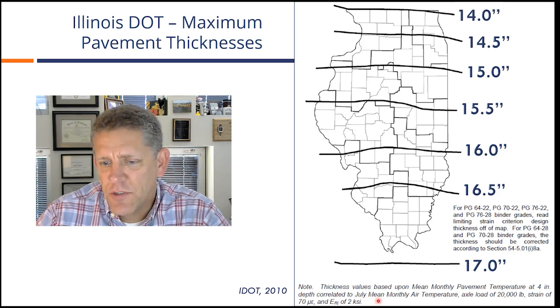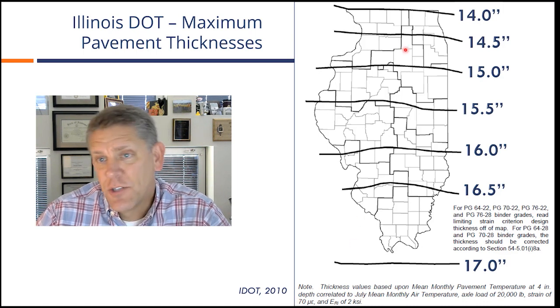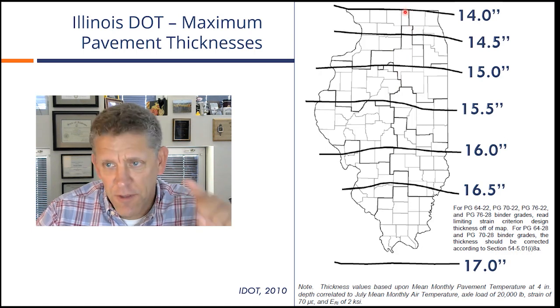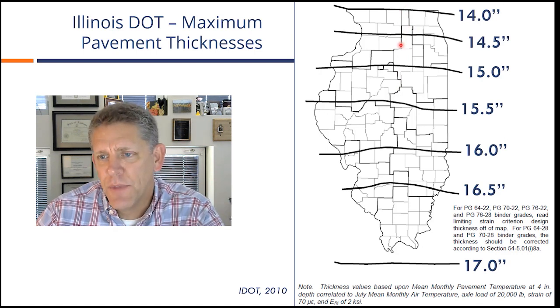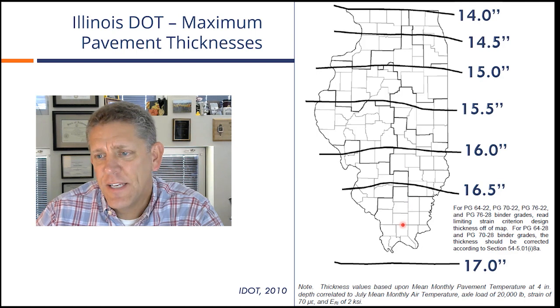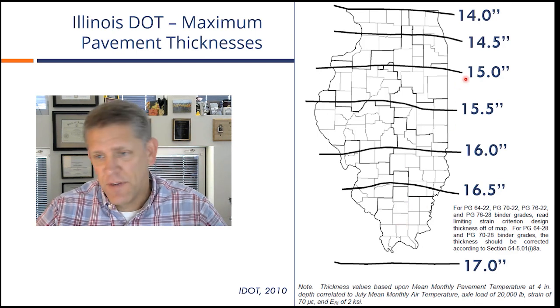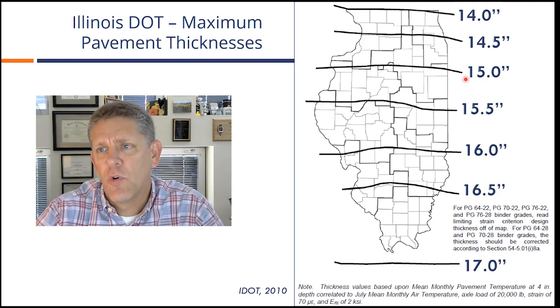The hottest month they use is July. They have some other assumptions in there. They use a pretty conservative strain level. And essentially they've gone through and done the computations, and the further north you are, the relatively thinner it is in terms of maximum thickness. And as you move further south, the thicker it gets, and that's taking into account some climate changes as you go north-south through the state. But they have, in terms of implementation, a really simple, straightforward way of doing this.